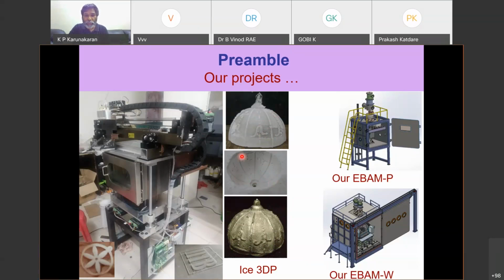Then, we went through the fundamental literature, found out that sublimation is possible. So we built a simple refrigerator and we applied a vacuum pump to that refrigerator, a combination of vacuuming with lowering the temperature enabled sublimation to happen. So when sublimation happens, before the ice melts, it vaporizes and then goes through the pores and then leaves. So we were able to produce a casting out of this. So this is a very interesting application.